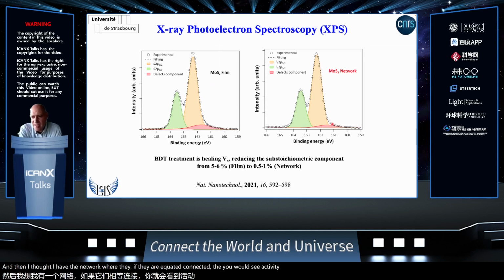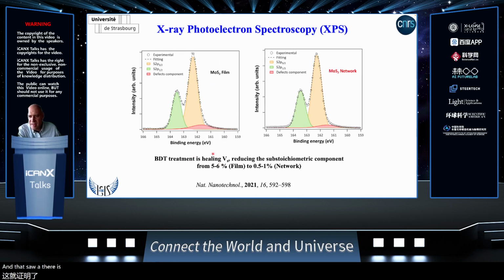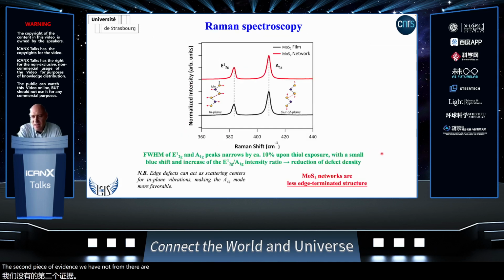You will see that upon benzene dithiol treatment, we have a reduction of this substoichiometric component, this flat band here. So there is a reduction of the sulfur vacancies from 5% to 0.5%. This is the first piece of evidence. The second piece of evidence comes from the Raman, where we focus our attention on the full width at half maximum of the A1g and E2g peaks, which we showed to narrow down by 10% upon network formation. Also the ratio between them shows an increase. All this can be explained by the reduction of defect density, in particular the fact that we have less edge-terminated structure. Indeed, most of the defects are on the edges, and most of the connections made with the molecule occur at the edges of the flakes.